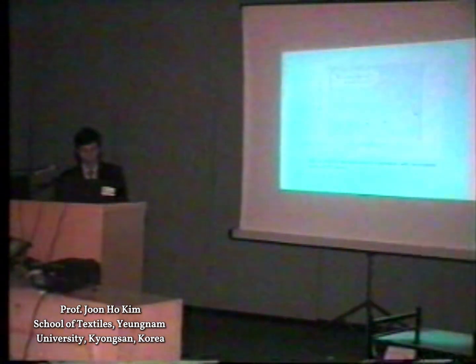This recrystallization process leads to an increase of the amorphous volume per crystallite. Since the number of crystallites decreases while their size increases, as a consequence, a more open structure is formed and the chemical can penetrate more easily, which leads to an increase in weight loss.